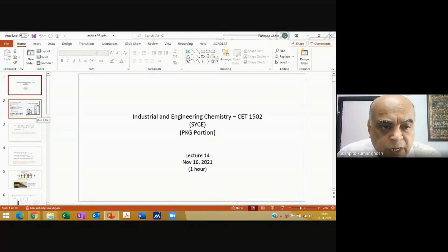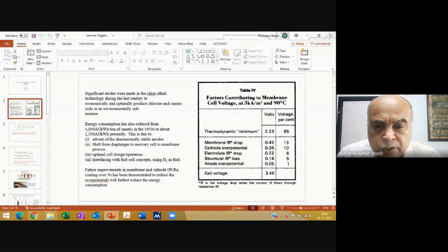Good morning. We were talking about the chlor-alkali process, and we had almost completed it. But let me show you some very significant developments which you can actually quantify. If you look at it, continuous improvements in the chlor-alkali process have been going on for over a century. Even in the 1950s, the power requirement was something like 4,000 kilowatt hour per ton, which now has come down to about half, 2,500 kilowatt hour per ton.